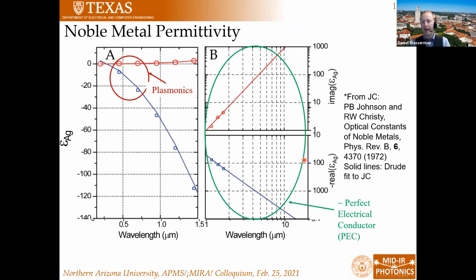Now, if we look at the visible wavelength range, in this range, we can actually see what we call a plasmonic response. And the reason why we can have this plasmonic response is because we can get subwavelength confinement of our modes, because our metal permittivity is negative, but not so negative that it looks like a perfect electrical conductor.